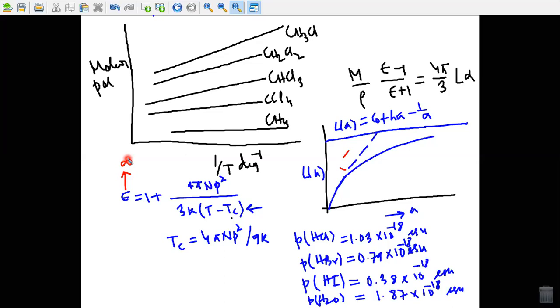But the fact is that using the known dipole moment of 1.87 debye units, we may estimate the critical temperature which would be expected for water. That is, if this dipole moment is used in this equation, then this Tc turns out to be 1200 degrees K, which is in striking contradiction of the fact that neither water nor ice is ferroelectric.